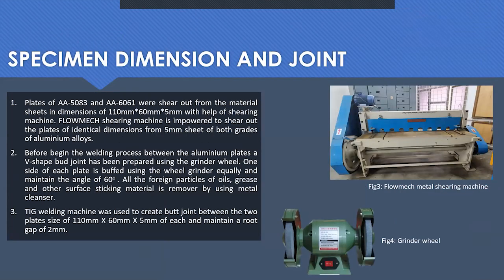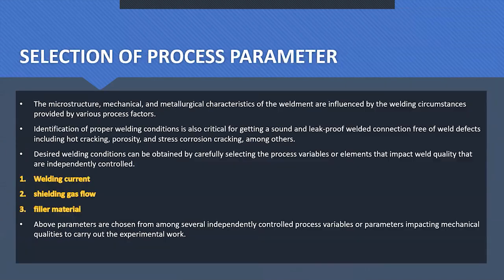Now come to the preparation part. The aluminum plates have been prepared in dimensions of 110 in length, 60 in breadth, and 5 in thickness using the shearing machine. And the V-shaped butt joint has been prepared using the grinder wheel, maintaining the 2 mm root gap, and then the TIG welding process has been done. The process parameters that we have studied are welding current, shielding gas flow, and filler material.